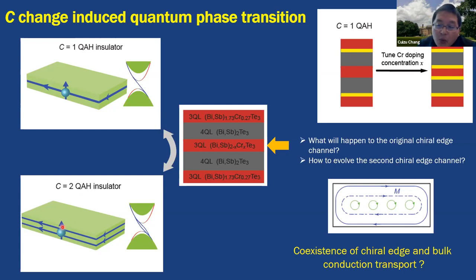But in the previous work, we just tuned this: at lower doping level, we realize C equals 1, and higher doping level is C equals 2. And here we want to systematically change the chromium doping level. But here the sample structure is a little bit different. We fix the chromium doping level in the top and bottom layers. We just change the chromium doping level in the middle to change the topology of the middle magnetic TA layers. And we want to take a look from the C equals 1 quantum anomalous Hall to C equals 2 quantum anomalous Hall.